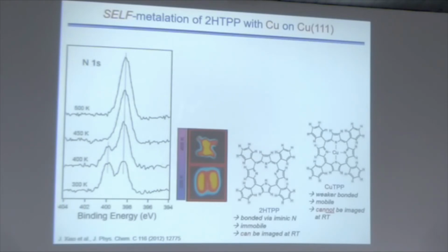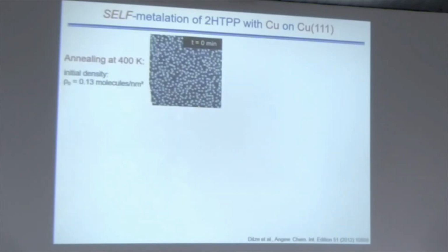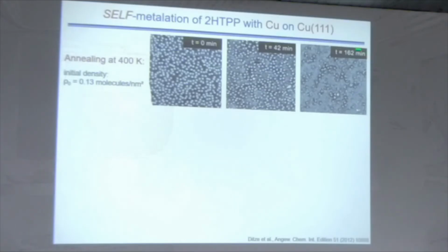Okay, this is really nice, because what you can do now is, if you are at room temperature and shortly heat to 400 Kelvin, some molecules react, you cool down, then you should have a decrease of the number of these species, and the others you don't see. And this is exactly what's shown here. So we put the molecules on the surface, and then we heat, and look how many of these protrusions, which are the free-base porphyrins, we have. So here we have all of them, because we did not heat, and then we heat for 40 minutes, and then for 160 minutes, and you see the number of bright protrusions gets less and less, and in between you see this greasy stuff. And this greasy stuff are the molecules that you cannot image.